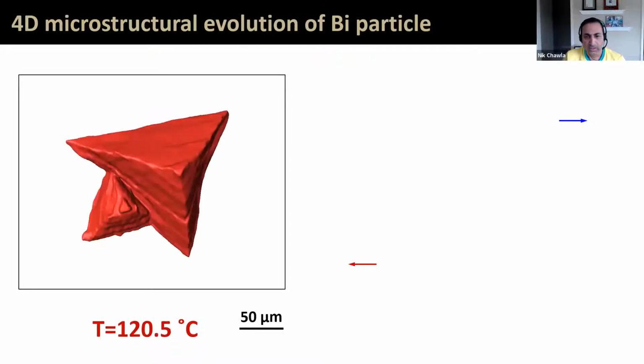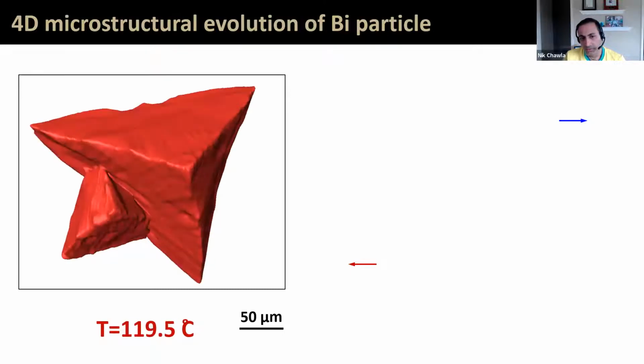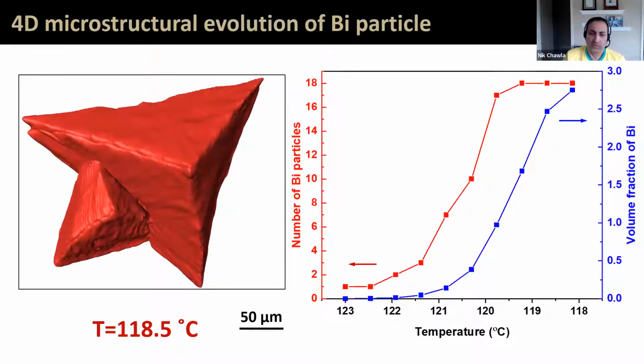Okay, so we can now take measurements of these particles, and Amaya has done a nice job of looking at number of particles as a function of temperature. So you see on the red here, the number of particles that are nucleating is initially very slow, and then it goes up quite a bit, and then at the solidification or a few degrees under the solidification temperature, you start to get what appears to be some coarsening and some coalescence of these particles. And along with that, of course, you're getting more and more precipitation of the bismuth. The volume fraction of the bismuth is also increasing.